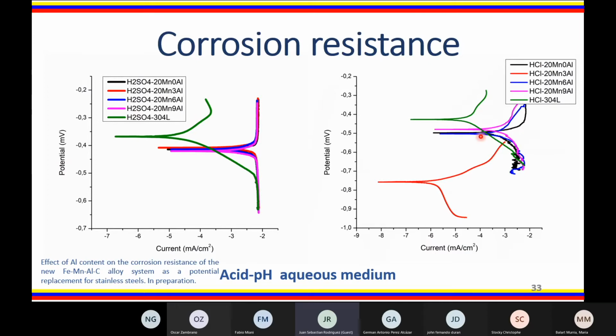The same can be observed in hydrochloric acid, where the behavior is very similar, although among the FeMnAlC steels, the 3% aluminum steel has more anodic values in potential and lower values in corrosion density compared to the other FeMnAlC steels. In general terms, it is concluded that the corrosion resistance of FeMnAlC steel is lower than stainless steel. It is possible that by varying the content of aluminum and manganese, or by adding some other alloying element, a composition of FeMnAlC steel with high corrosion resistance could be reached.